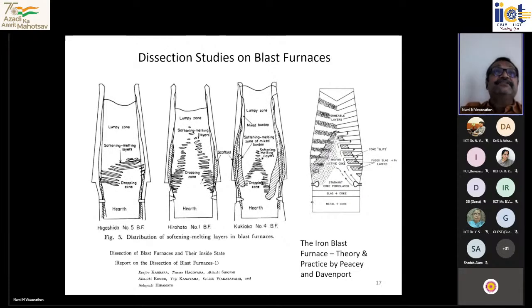And what the Japanese did, somewhere in '75 or so, we didn't know what is happening inside the furnace. And what the Japanese did was actually to quench the furnace. They pass the air, oxygen, air, etc. from the bottom, and there is a lot of burning that happens, and that is what drives the whole furnace. So instead of that, they injected nitrogen so that the whole furnace can be quenched very fast. Imagine, 1,200 crores worth of things, and they did not stop at one furnace. Some 7, 8 furnaces were quenched. This is the level of scale of experiments done by the Japanese.